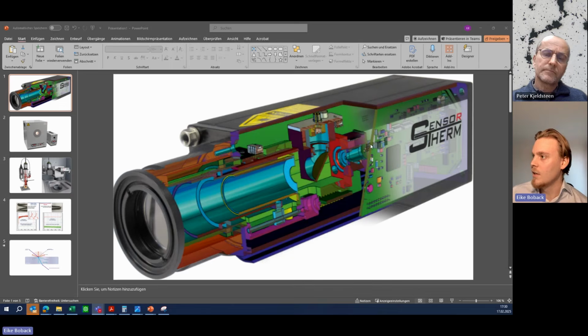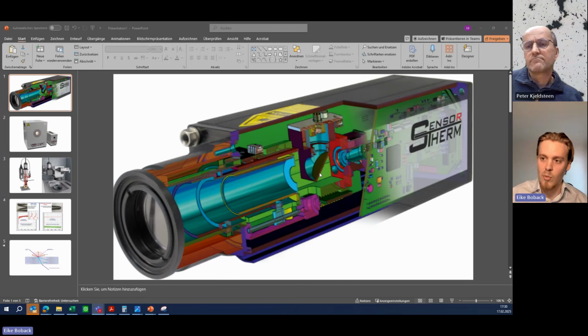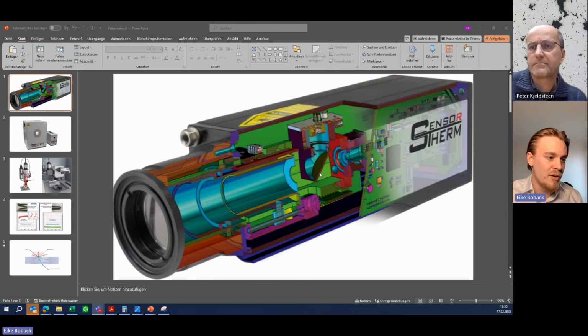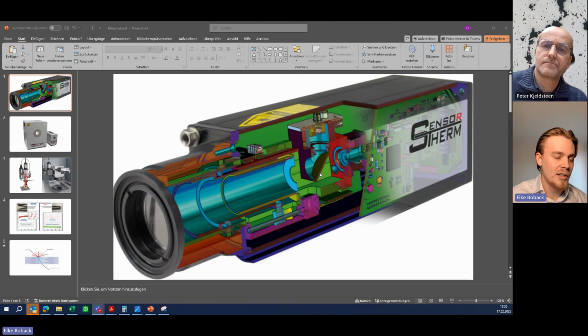You can see the inside, and there you have one detector, and there you have the second. So we're measuring with 2 different wavelengths, beam splitting with a dichroic mirror, and then we get different wavelengths, measuring both at the same time. And we are measuring not the radiation, but the difference in the emissivity at these wavelengths. Then you get a whole new value, less sensitive to variations in the emissivity. So you can buffer a bit of the effects, but not the whole process. Some adjustment has to be done too.